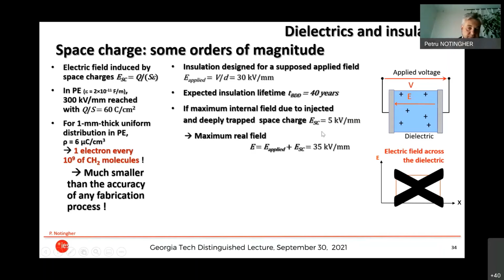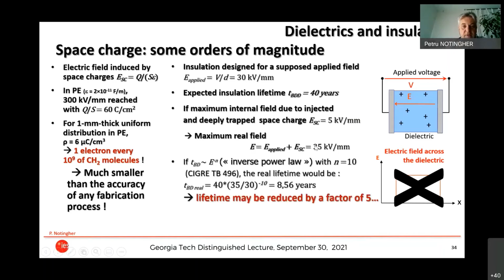So it doesn't look like a lot, but if you look at what happens with time, at the time to breakdown, I took this one because it's one which is used for high voltage cables. By increasing the field from 30 to 35 kilovolt per millimeter, instead of 40 years of service, you'll have only 8 years and a half. So we will reduce your lifetime by a factor of 5.